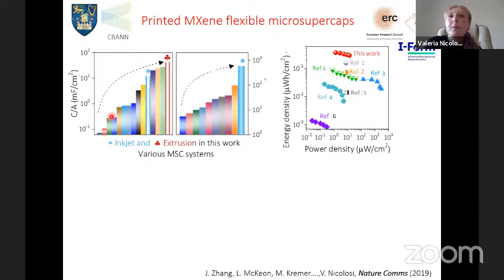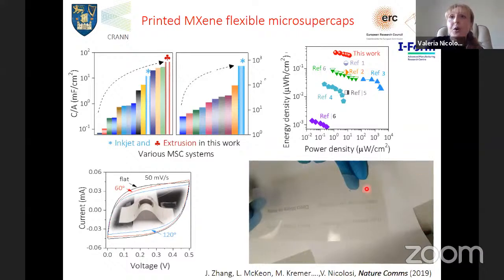Here we compared the areal capacitance of our devices, inkjet printed and extrusion printed, to other devices that were made in literature by other methods. And again, we could reach much higher areal capacitance. And here is the energy density as a function of power density, so a Ragone plot. These are all different references that we found in literature, the closest ones. And here is this work where we could really store way more energy, and we could achieve a much faster response, so power density.